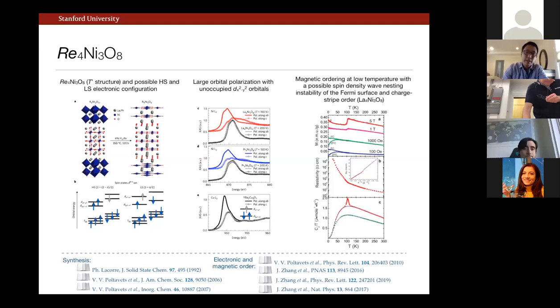The brief statement is that almost every ground state other than superconductivity has been observed, namely insulating and metallic ground states. And they're very susceptible to density wave instabilities, both in the spin and charge sector. If you naively take the electron count given by the crystal structure, these would generally be overdoped, right? So it's 1 over the number of layers. So this would be something like hole doping to the level of 1/3 or 1/2 in the bilayer case.